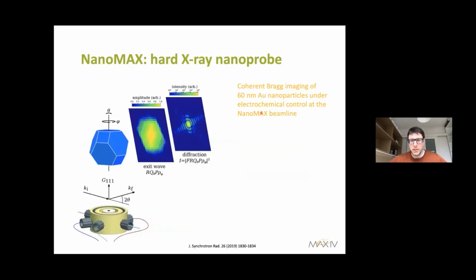Another experiment that was done at NanoMAX was a proof of principle, but I think it's quite important. It shows that this particular type of measurement could be done after overcoming some of the small difficulties. This is the coherent imaging in Bragg conditions of gold nanoparticles, and this is done in an electrochemical cell under operando conditions. So you have an electrochemical cell, and you apply voltages, you do some electrochemical reaction, and you measure, in this particular case, the stress distribution within a series of nanoparticles.